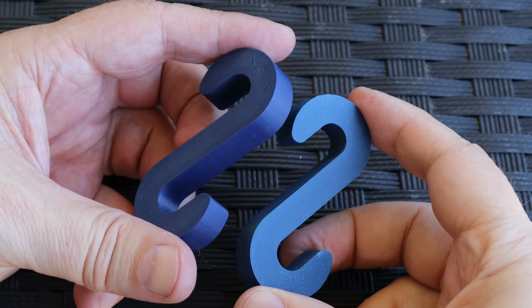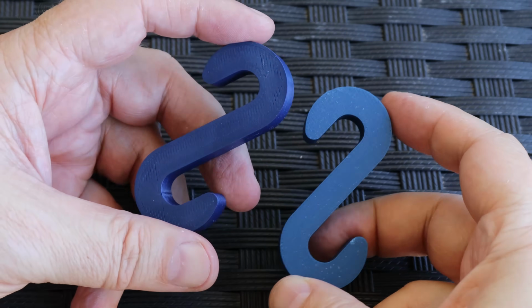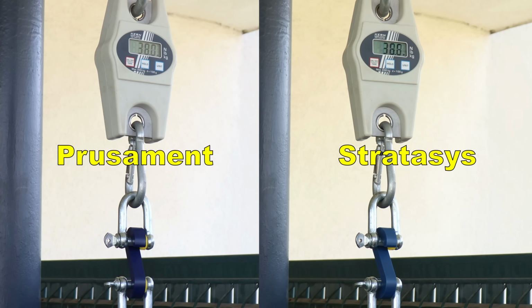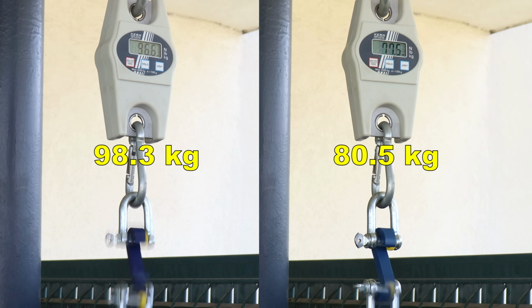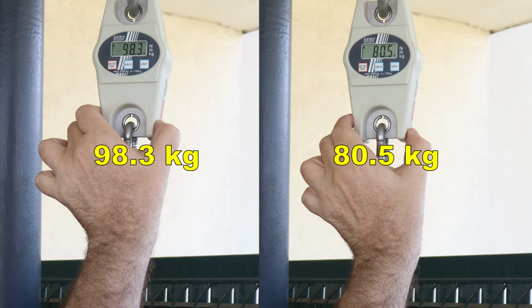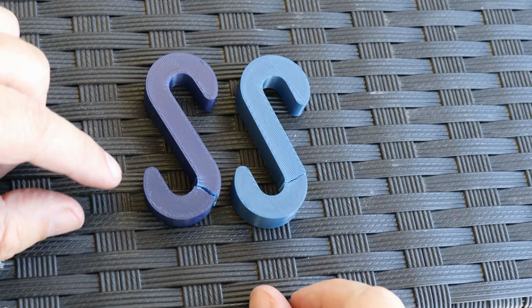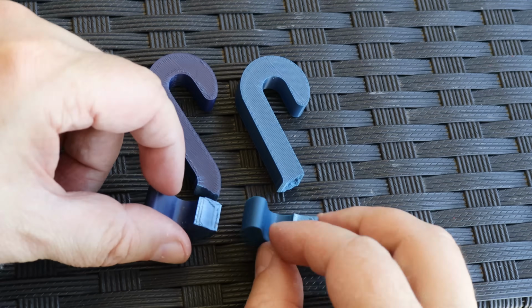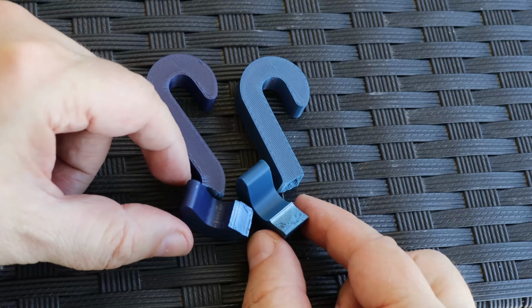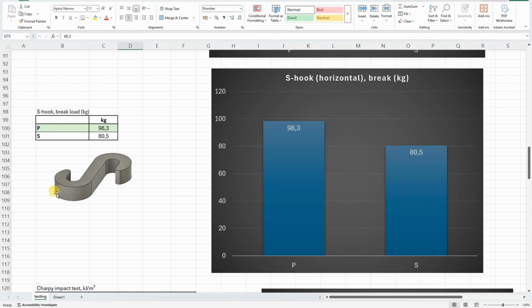And now S hooks, these are printed in horizontal position. Side by side, 2 materials. This time the break was in a little bit different location. This test is less sensitive to the print settings and gives us a clearer picture of the material properties, and in this case the Prusament was much better.